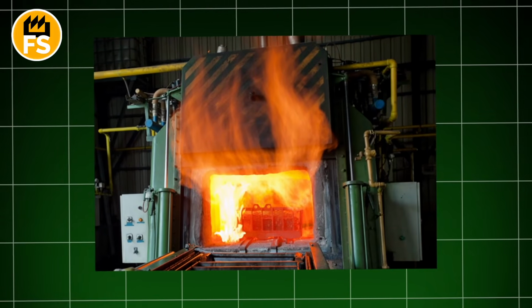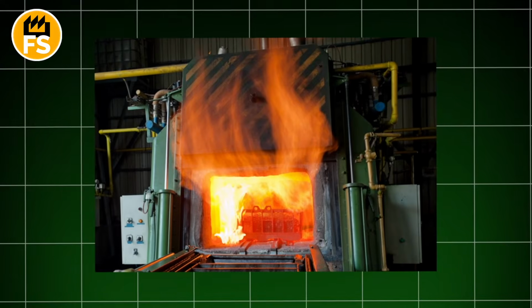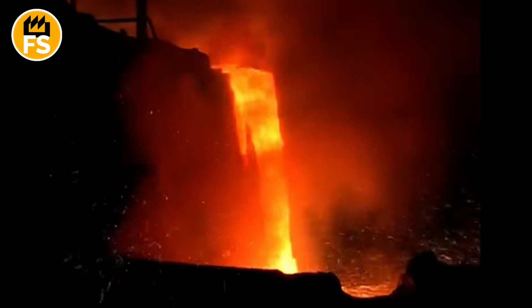To give them strength, they are sent to a furnace. But this is not an ordinary furnace. This is a high-temperature furnace, filled with hydrogen to prevent oxidation. There, at a temperature of over 3,000 degrees Fahrenheit, these pellets are baked for many hours.